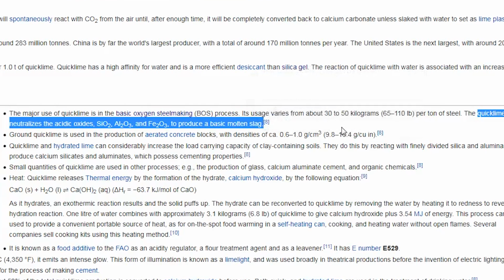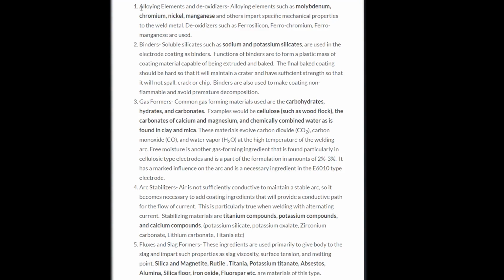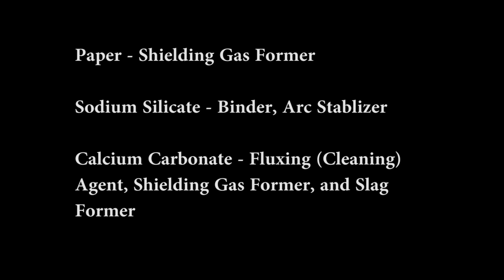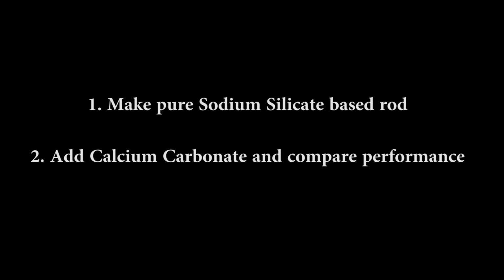See, when you weld, the ingredients used for the coating of the rod will each have a purpose. There are alloying elements and deoxidizers, binders, shielding gases, arc stabilizers, fluxes, and slag formers. Now, to sum this all up, we are going to be using paper, sodium silicate, and calcium carbonate to make our rods. So my idea was to follow the first patent I showed you and make a pure sodium silicate based electrode and see how it performs. Then we will add the calcium carbonate and compare the performance.